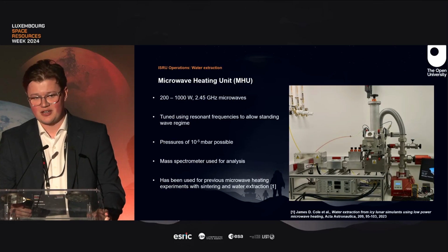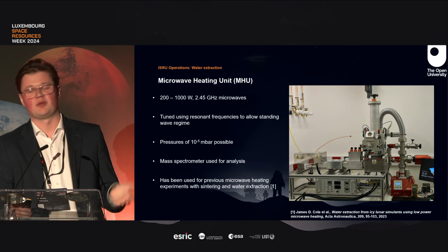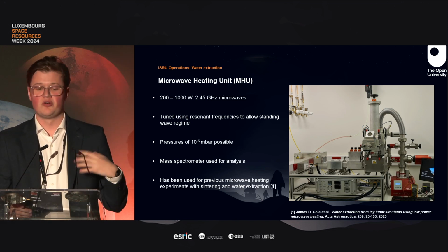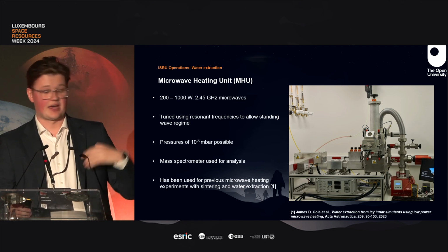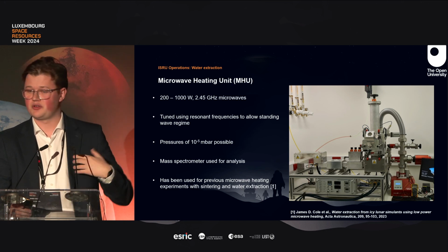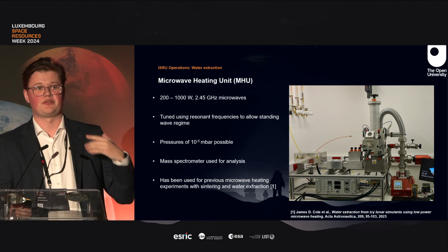The microwave heating unit is attached to a vacuum system, so we can go as low as 10 to the -5 millibar, and a mass spectrometer is also attached to analyze any volatiles that are being released. It's previously been used for sintering experiments, and so the initial part of my PhD was to adapt the system for water extraction, and that is the process described in my first paper, where I looked at the differences in extraction using different water contents and different mineralogy simulants.